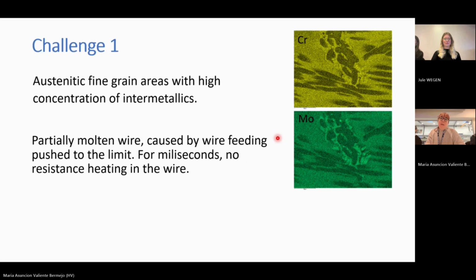Then when we looked closer into these fine-grained areas, we found that they were mainly austenitic areas with a high concentration of intermetallics all around. These intermetallics are highly enriched in chromium and moly. As a consequence, all the areas around that are depleted in these elements, and that is why they become less good for corrosion properties. But the reason was, as Peter also explained, this partially molten wire. We were feeding the wire, but not all the wire was fully molten. It was identified that this feeding system was pushed to the limits, and for some short times, I don't know if the milliseconds are accurate, there was no resistance heating in the wire, and then it was not really melting properly. So that was the first challenge we found, and it was very interesting.